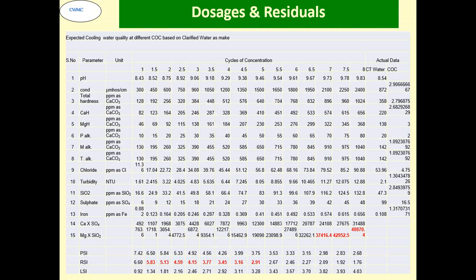This is the typical cycles of concentration that has been carried out, and normally what you see down below, the Ryznar stability index in the red color, I have put 2.91. Normally it is not recommended that we go beyond RSI of 3. RSI lower than 3 is a very difficult thing to be treated by chemical treatment. We have to then go for the softening and other things to operate on that.